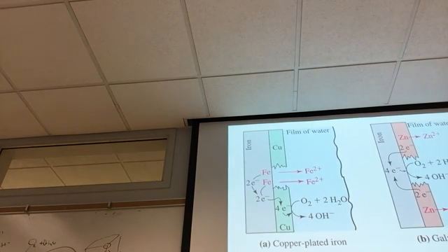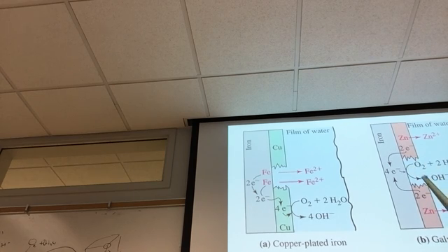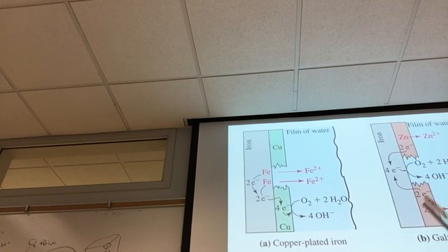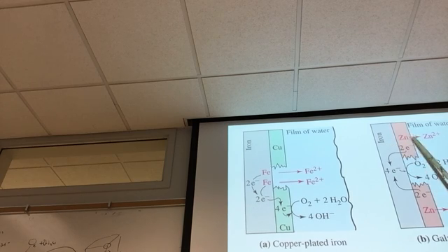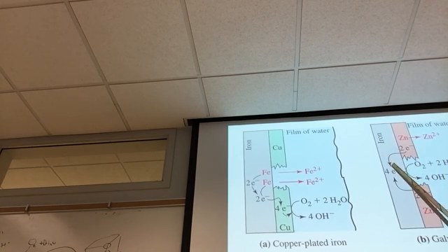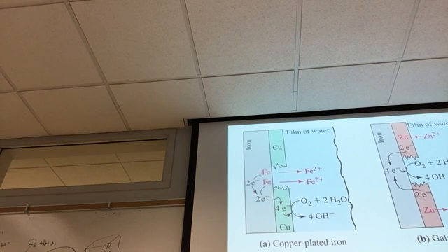So here we have galvanized iron. With galvanized iron, the coating doesn't have to be perfect. In fact, there's no problem if there's gaps or cracks in the coating here. Because what's going to happen is you have a choice of oxidizing iron or zinc. We're going to oxidize zinc because zinc has a higher oxidation potential. Zinc gets oxidized, those electrons go to the cathode. The cathode now is iron, where oxygen is going to pick up those electrons and form hydroxide in neutral solution. And so as long as we have zinc here, the iron's protected.